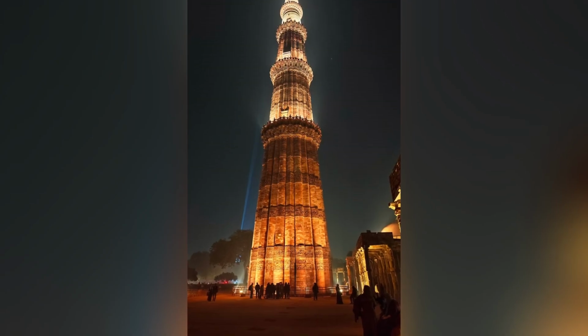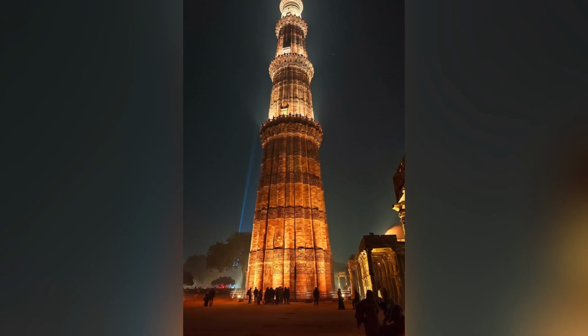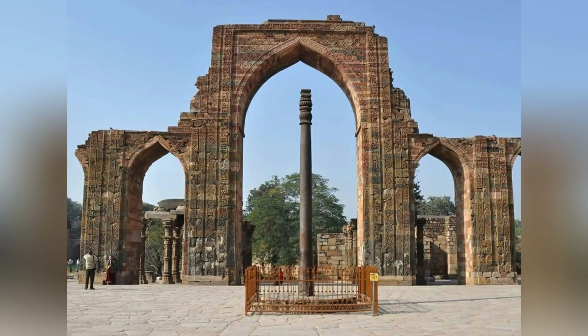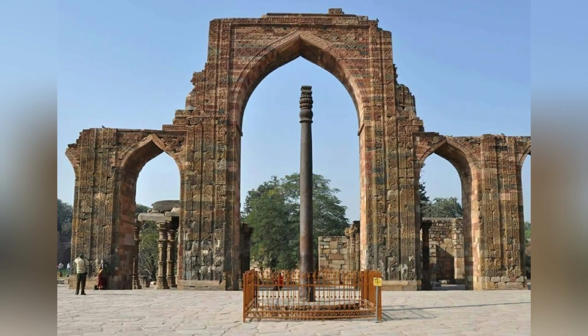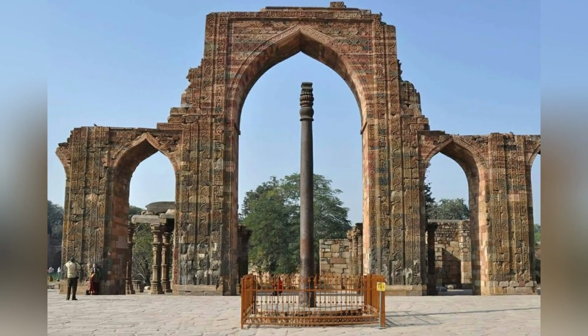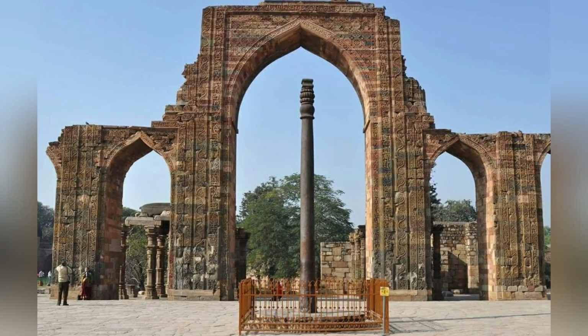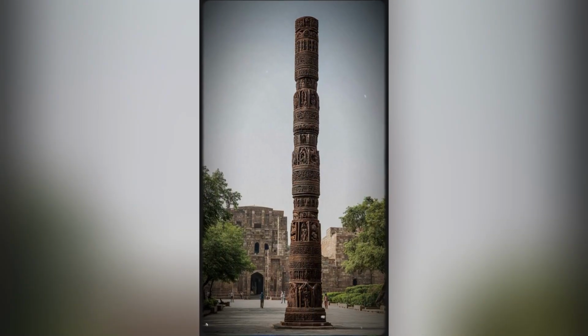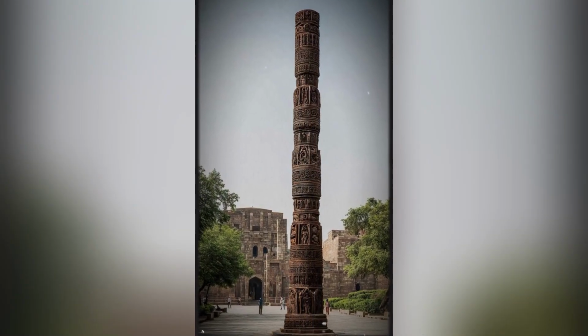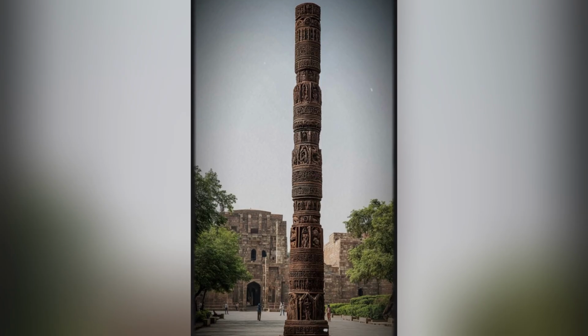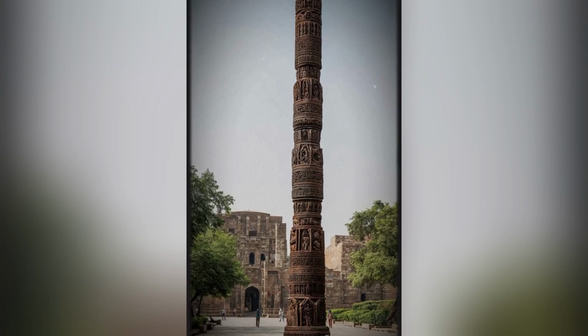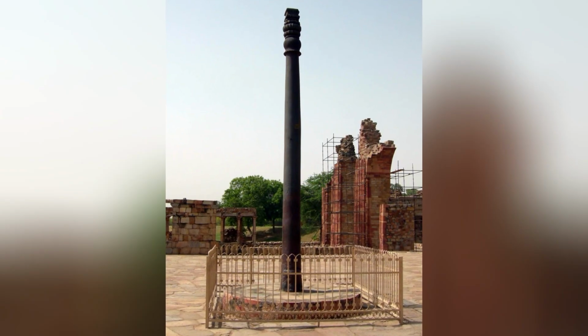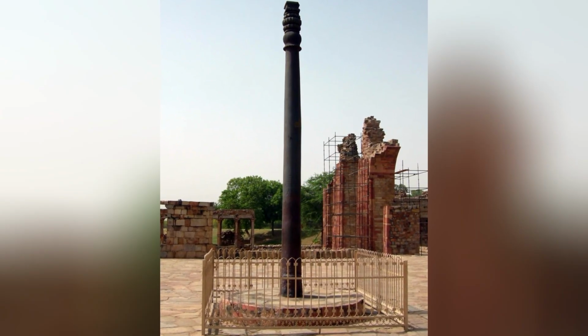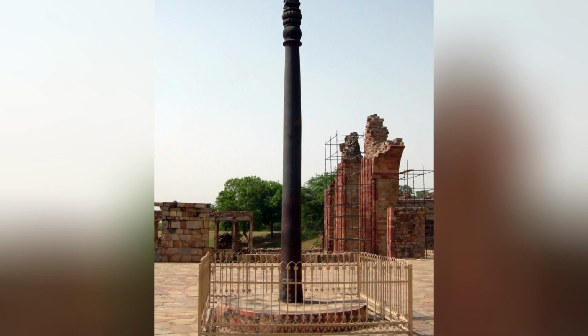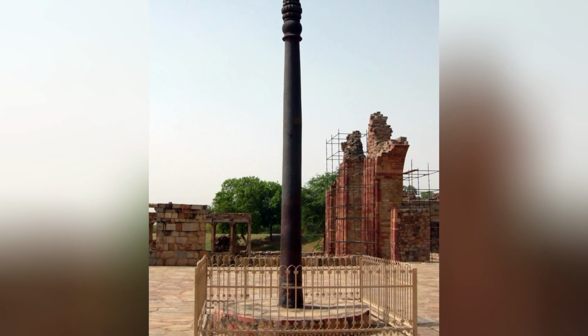Balasubramaniam has investigated this question by conducting accelerated corrosion tests on phosphorus-rich iron in simulated climates of varying humidity and temperature, and his results suggest that the cyclic wet-dry exposure is indeed essential for the formation of the protective film. In a continuously wet climate, the phosphorus dissolves continuously without having the opportunity to crystallize and to form a dense film, and in a continuously dry climate, the moisture that is needed to initiate the phosphorus reactions is not available.